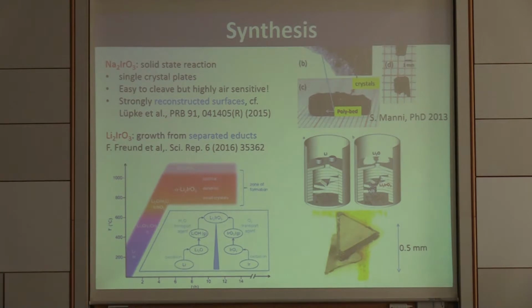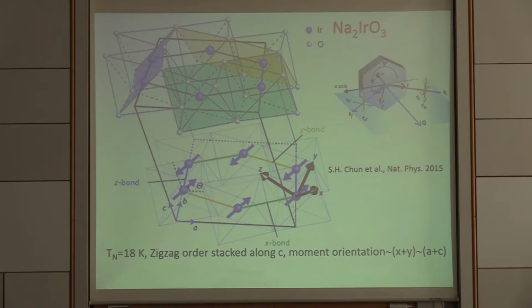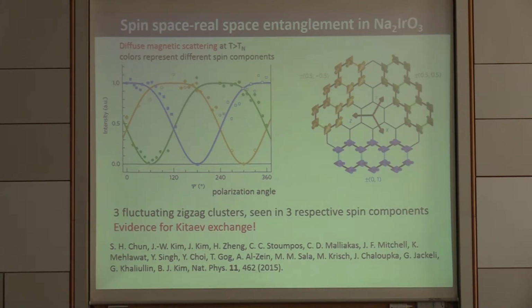And these crystals then made it possible to determine the magnetic structure of this material. So for sodium iridate, we have a commensurate ordering, a zigzag magnetic order, where we have antiferromagnetic coupling along the Kitaev-type Z bond, which equals the crystallographic b direction. Such an order you would also get with an ordinary Heisenberg J1, J2, J3 model on a honeycomb lattice, but there is evidence that the Kitaev-type interaction is important in this material.